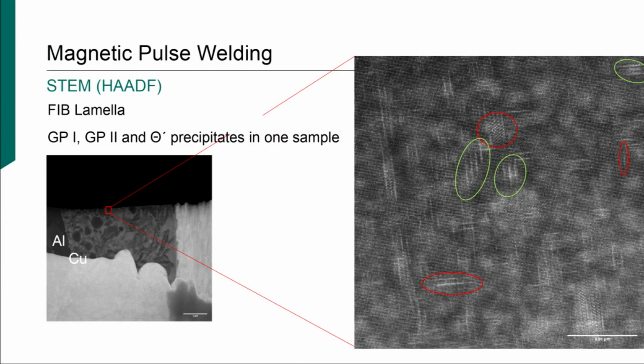And you find microscopic theta prime phases here. Normally they are much smaller, much larger, sorry, and also have a larger extension. So they are nearly as wide as long here, or maybe 1.5 or so. This would more correspond to what you showed for the interface anisotropy, and this, what you typically find, this very